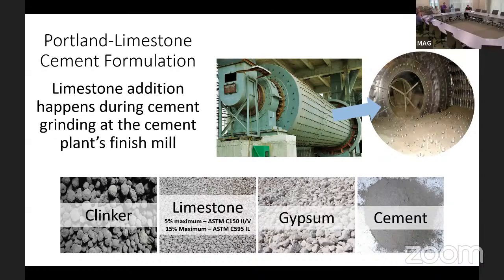Very similar, the same clinker, the same gypsum, the same limestone. The only difference for the C595 is the proportioning. So you're going to reduce your clinker factor lower to say 80 to 85%, and you're going to replace that with limestone. The limestone isn't calcined, so it has a lower CO2 footprint than clinker. Similar gypsum, and you're going to get the same cement that performs the same. The only difference is one has a global warming potential of say 900 or 1,000, and another one has a 750. So maybe not that exaggerated. You're looking usually at about a 10% reduction in CO2, just switching cements from C150 to C595.